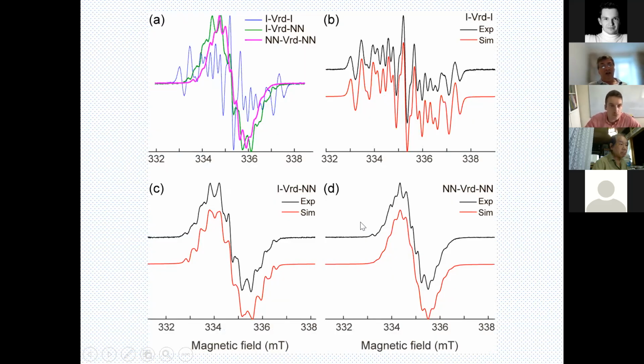We thoroughly characterized all compounds, the radicals and triradicals, with all spectroscopic methods. I show you EPR data. You see that for the diiodo derivatives and monoradicals, we have rather complicated EPR spectra with many lines. After introduction of one and two nitronyl nitroxides, we obtain narrow and less resolved EPR spectra.